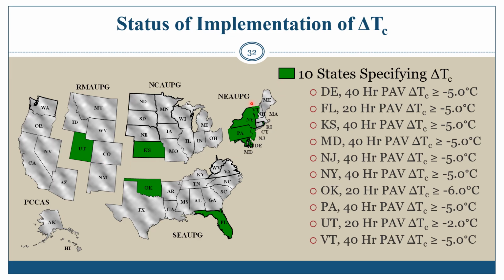The 10 states in green are the states that have delta TC specifications. Delaware, 40-hour PAV, minus 5.0. Florida, 20-hour PAV, minus 5.0. Kansas, 40-hour PAV, minus 5.0. Maryland, 40-hour PAV, minus 5.0. New Jersey, 40-hour PAV, minus 5.0. New York, 40-hour PAV, minus 5.0. Oklahoma, 20-hour PAV, minus 6.0. Pennsylvania, 40-hour PAV, minus 5.0. Utah, 20-hour PAV, minus 2.0. Vermont, 40-hour PAV, minus 5.0.